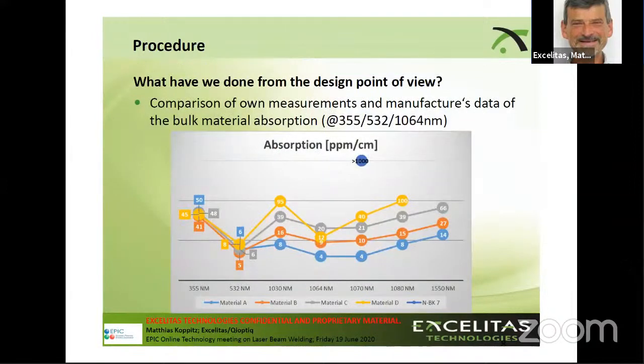The next thing is very important for high power applications as well. The homogeneity was especially relevant for the spot quality, but now we're going to the absorption of the material. Here we made a lot of extensive measurements to qualify different materials; at the end we qualified 4 different fused silica materials from 4 different manufacturers. You see a very big variation, especially for the Nd:YAG laser wavelength, the first harmonic wavelength: in between 1030, this laser, Trumpf, 1064, 1070, 1080, IPG, and so on. You see there is material in the market, a very common material used in the laser and optics market, with a big variance of absorption.